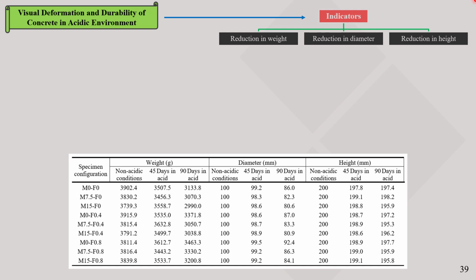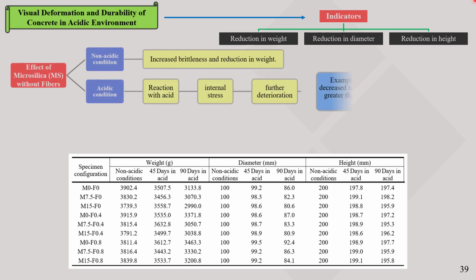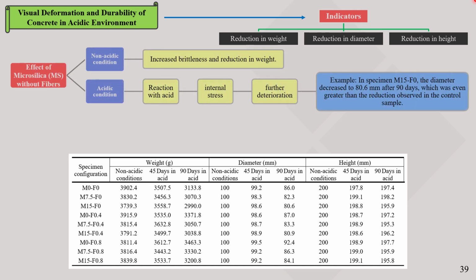We now move on to visual deformation and durability. In this experiment, three parameters were examined: weight loss, reduction in diameter, and reduction in height. Regarding the effect of microsilica without fibers, under non-acidic conditions, replacing part of the cement with microsilica caused the samples to have slightly lower weight compared to the reference sample.